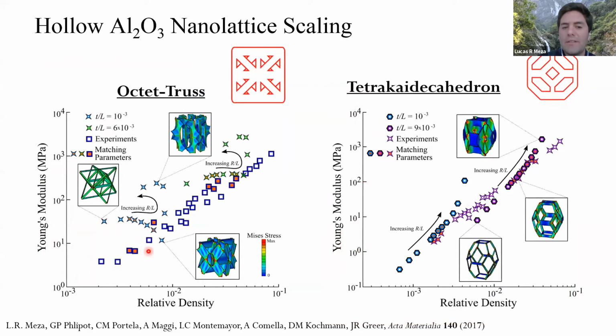When we started looking at different property spaces, we actually saw pretty drastic shifts in behavior. There were awkward or odd transition points where at the same relative density, you could get an order of magnitude change in properties by changing exactly how the load was being carried by the shell. Here you have load concentration points, sharp corners. Here it's rounded out enough that you transfer the load differently in the shell wall, and you're able to drastically increase your performance.